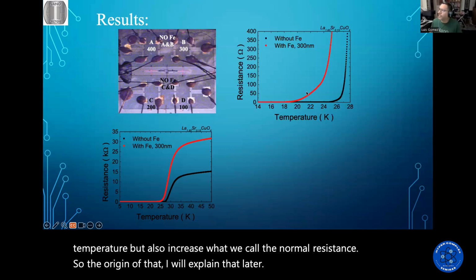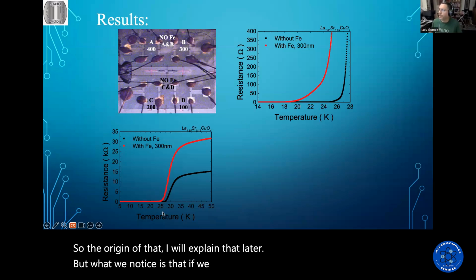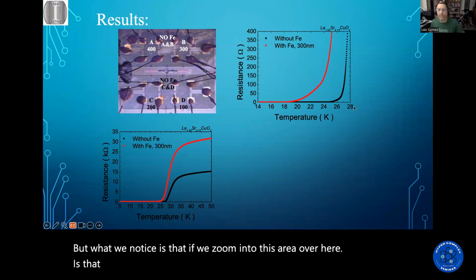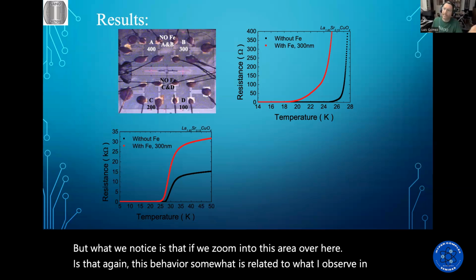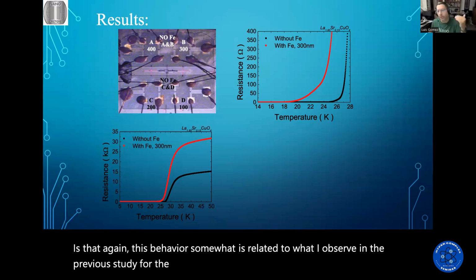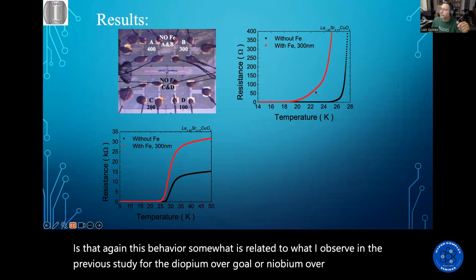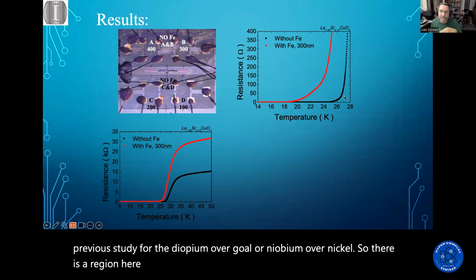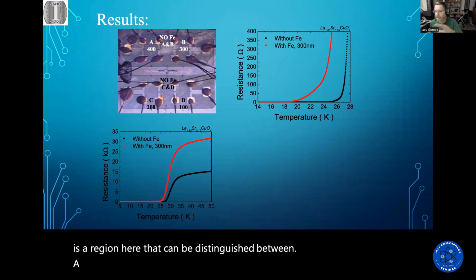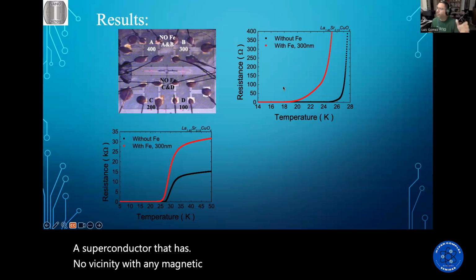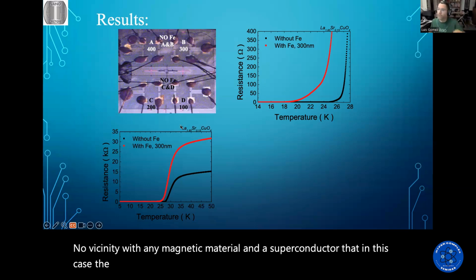But what we notice is that if we zoom into this area over here, again, this behavior is somewhat related to what I observed in the previous study for the niobium over gold or niobium over nickel. So there is a region here that can be distinguished between a superconductor that has no vicinity with any magnetic material, and a superconductor that, in this case, has the magnetic material right on top of it.